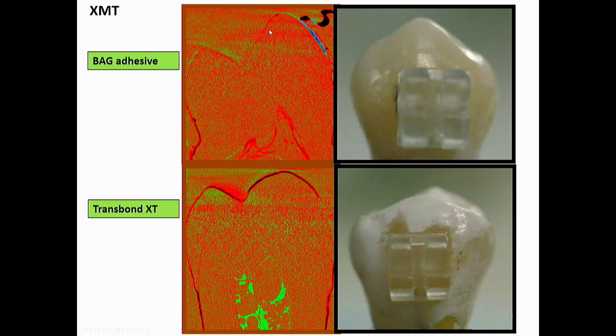This is in contrast with what happens with conventional orthodontic adhesive, which was Transbond XT, and you can see whitening over the tooth surface, all over the tooth surface, which is a result of pores created in the enamel as a result of demineralization. And you can also see this as a dark line on the enamel surface in the difference image from the X-ray microtomography.